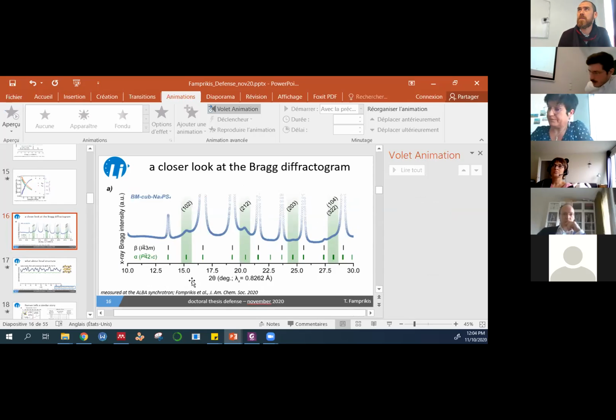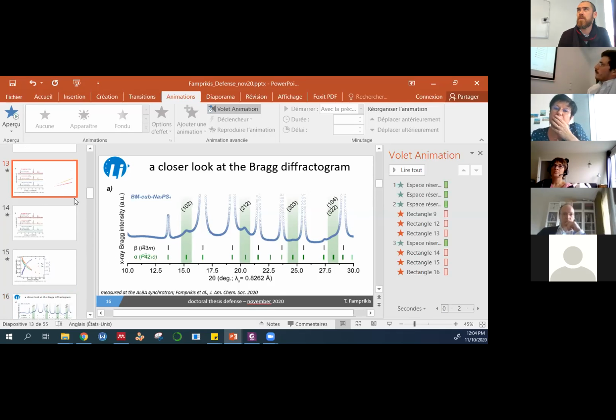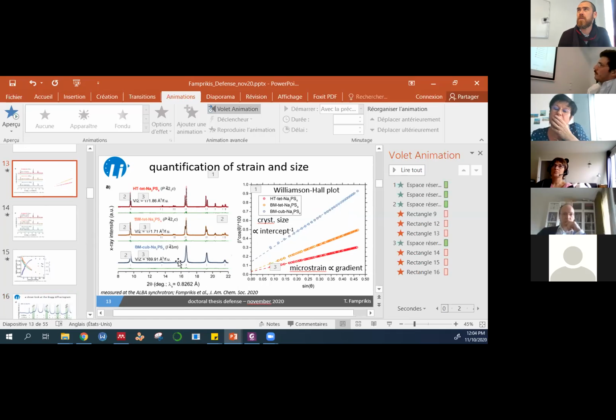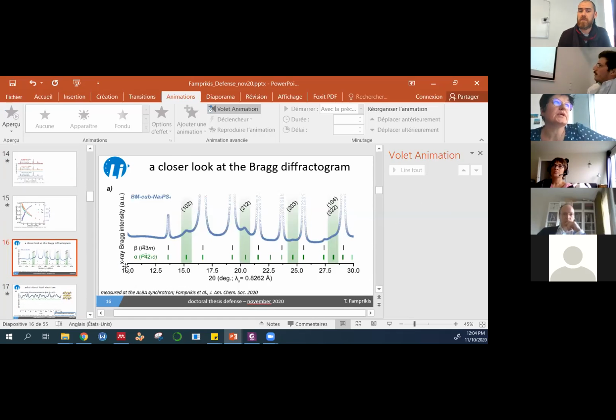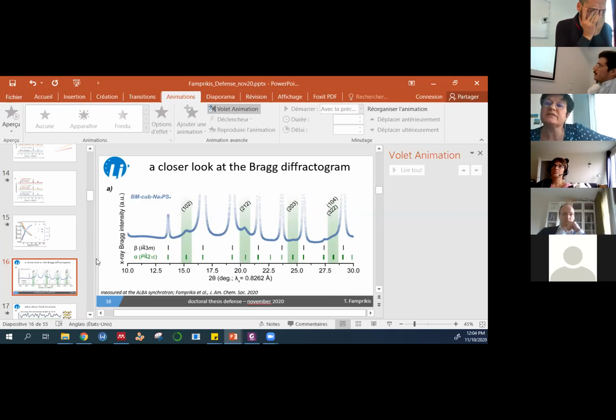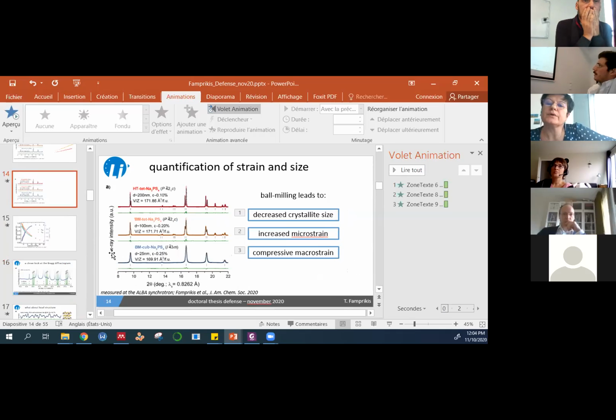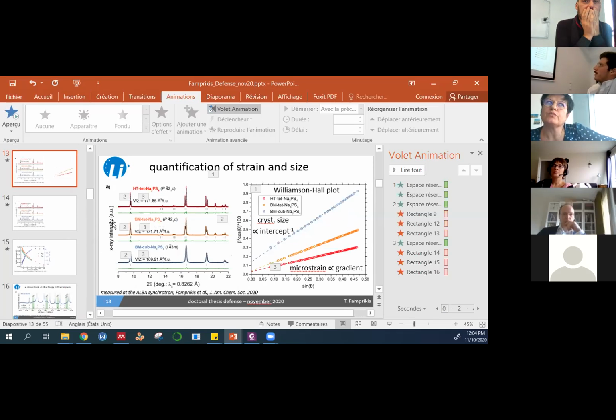The microstructure analysis I showed before and the Williamson-Hall plot come from the fits shown here. So the blue sample, the ball mill sample, is fitted in the cubic space group. To calculate your Williamson-Hall plot, you consider the calculated profile, in fact.